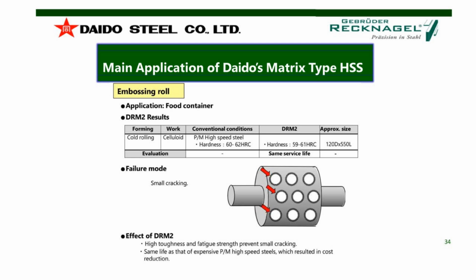This is a little bit special, an embossing roll. I could imagine this is maybe from a customer in Italy, but I'm not sure about it. It's a cold rolling of celluloid material for food containers. In this case, it wasn't the goal to bring up the tool lifetime, because the customer was using a very expensive powder steel grade with a hardness of 60 to 62 HRC. As you can see in the table, the diameter was very big, 120 millimeter, and the length 550 millimeter. That means this tool is very expensive, and his focus was to save some money during the process, so he switched to DRM2. The service lifetime was on the same level, but he saved a lot of money because DRM2 is much cheaper than a powder steel grade.